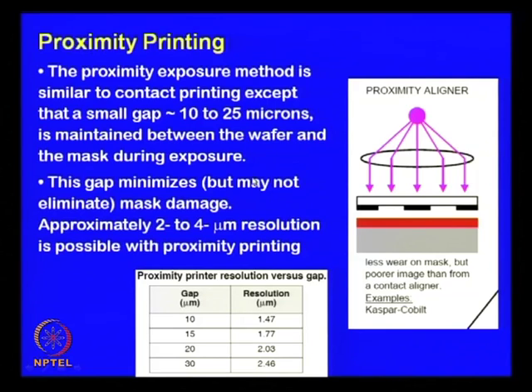Now, in order to overcome the possibility of a likely mask damage because of the debris, the concept of proximity printing started getting more popular. In proximity exposure method, it is similar to contact printing, except that a small gap of let us say 10 to 25 micron is maintained between the wafer and the mask during exposure. This gap minimizes the mask damage, not fully eliminates, but minimizes the mask damage.